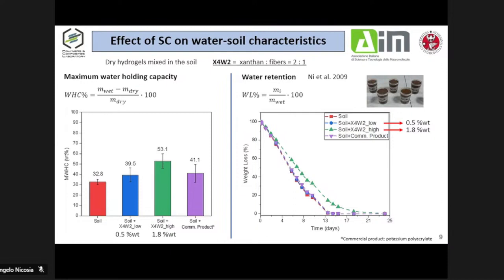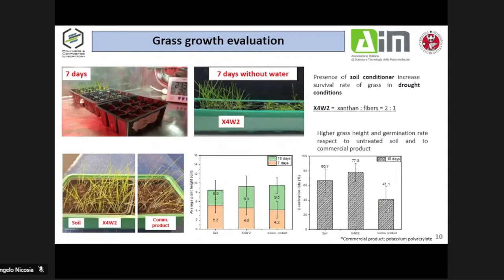We also investigated whether the water can remain in the soil, so we measured the water retention. And we found good results in this case too, for amounts of less than 2% in weight with respect to the soil. Then we made a practical application on grass. We planted grass seeds in the soil, and with our material the plants could survive even under drought conditions, without water. We also compared the material with the commercial product, and found better results in terms of germination rate, which is the ratio between germinated seeds and planted seeds.